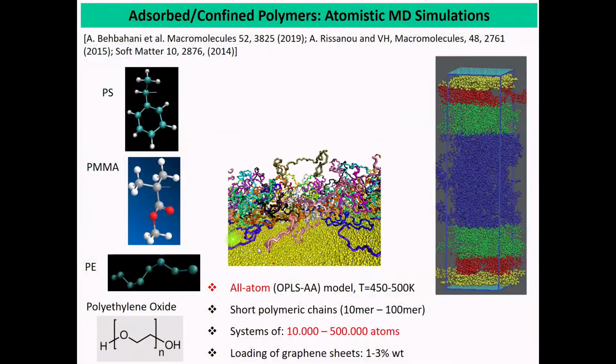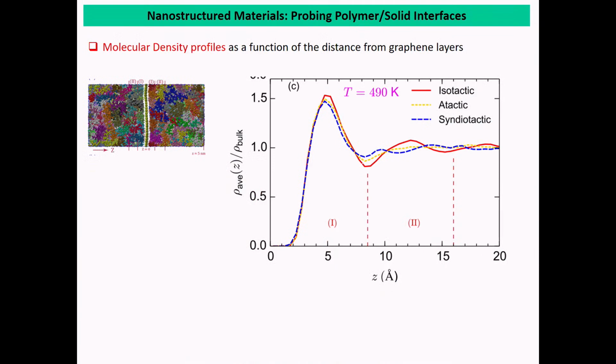Okay, this is again a very important question. So this depends entirely on the problem under study. Typically, because I try to not include many equations, let me just give you an example. So here we perform the simulations, and exactly as you say, the simulations can be very long. So let's say that we try to calculate one property like the density here. So the standard thing that someone could do is to examine the time scale above which this profile, which is the average density, does not change in time. So it's an average quantity, not time dependent.